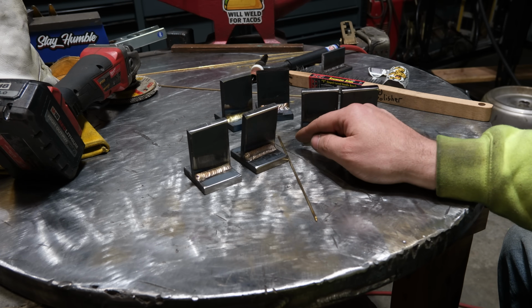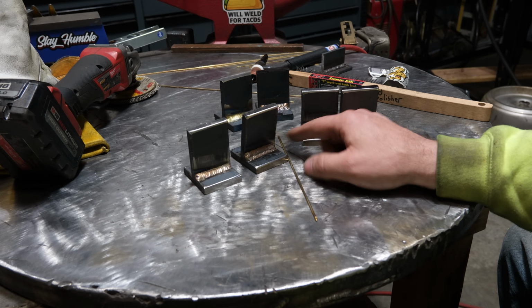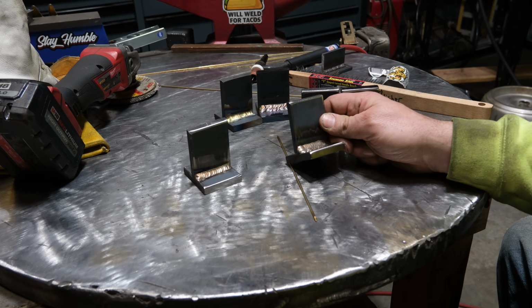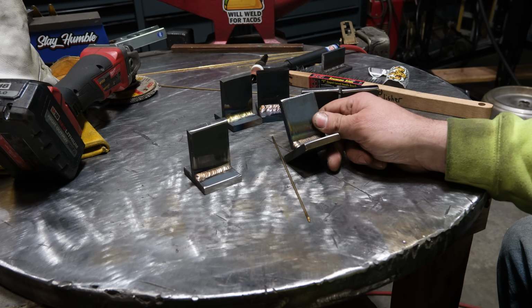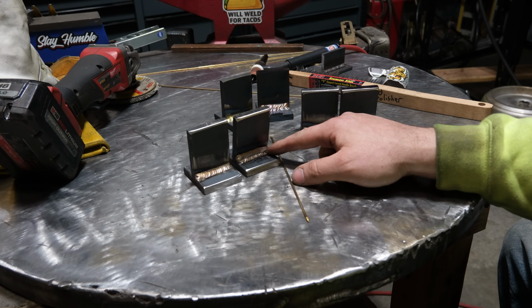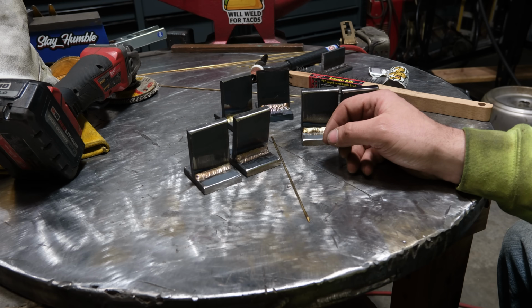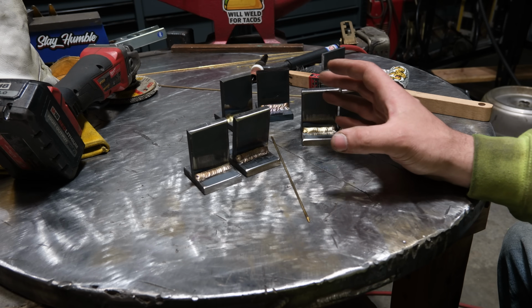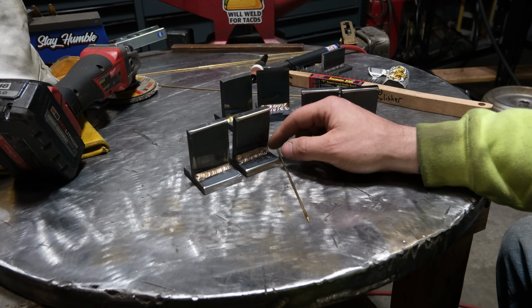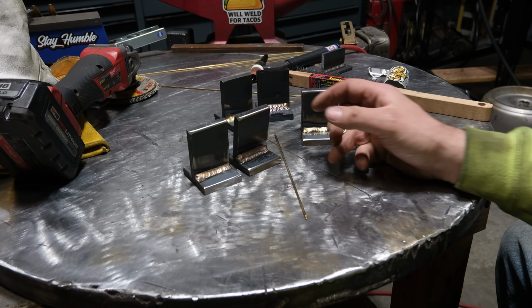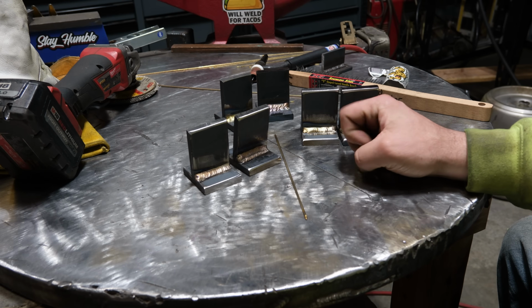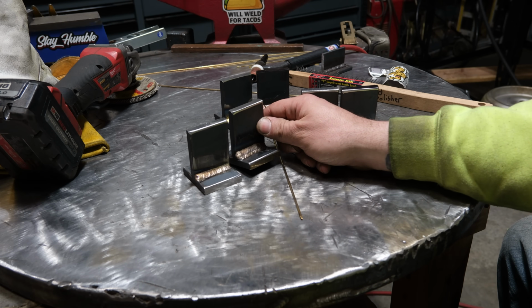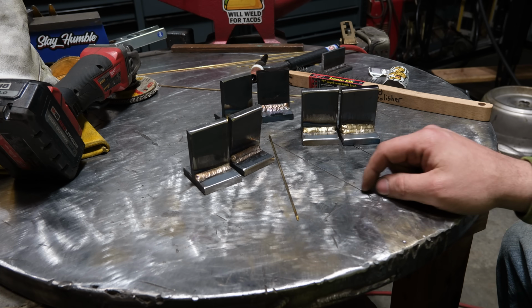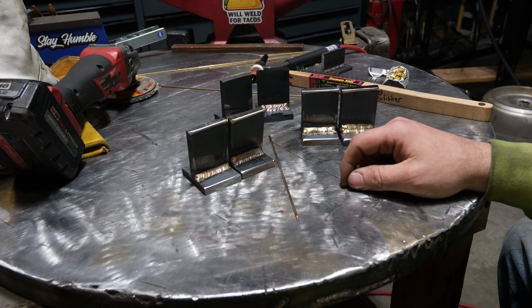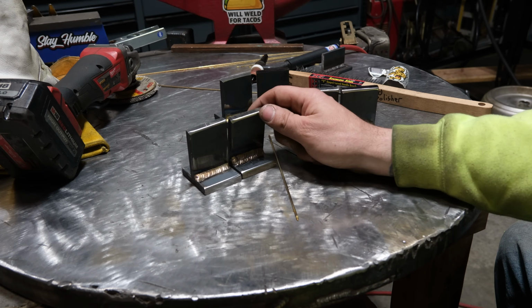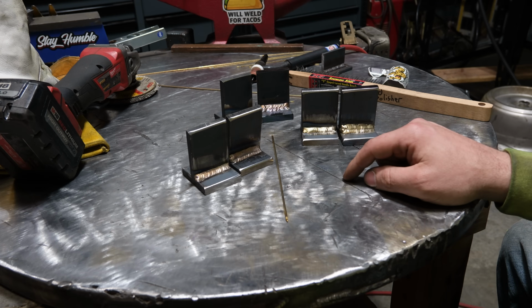I ran a pass, gave it a couple of minutes, ran a pass, probably didn't give it enough, and ran a third pass. And you've got to be careful with not overheating your base material as well as the bronze itself. This stuff you can't really move fast. You kind of want to go low and slow, per se, like you want to keep the heat on it and travel at a reasonable pace. This I probably sped up a little bit, and the faster it cools, the higher likelihood I think you're going to get of cracking. And I don't really know for sure if that is a crack. I mean, I can't see it, but I guess we'll find out. The other interesting thing too is the silicon bronze seems to pull a lot more.